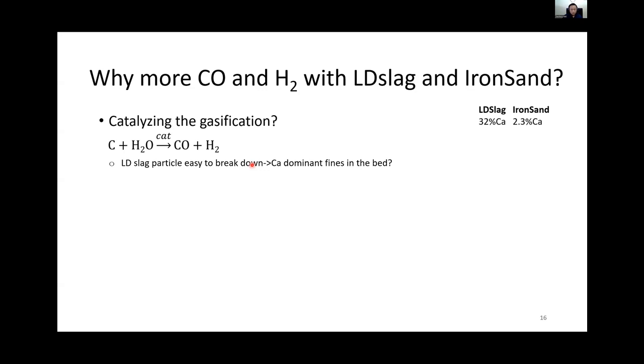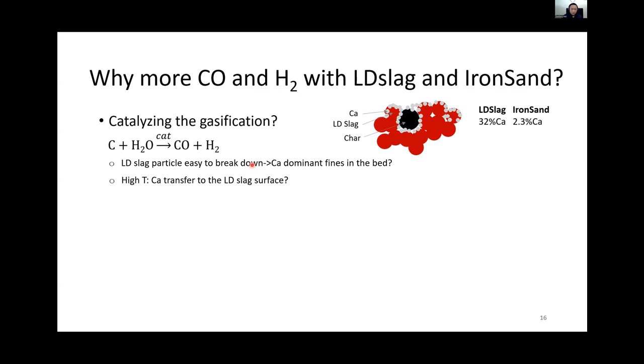So when it breaks, there's a chance to form maybe calcium dominant particles or fines in the bed. And second, at high temperature, calcium may have a better mobility and it can transfer to the oxygen carrier surface. So calcium may be on the oxygen carrier particle surface, but we probably also have kind of free calcium dominant fines.